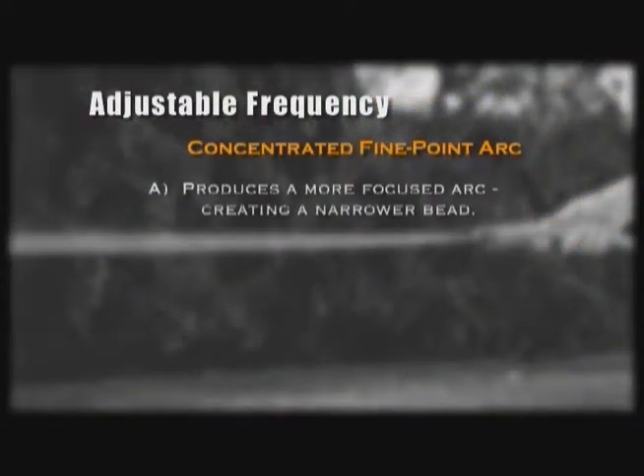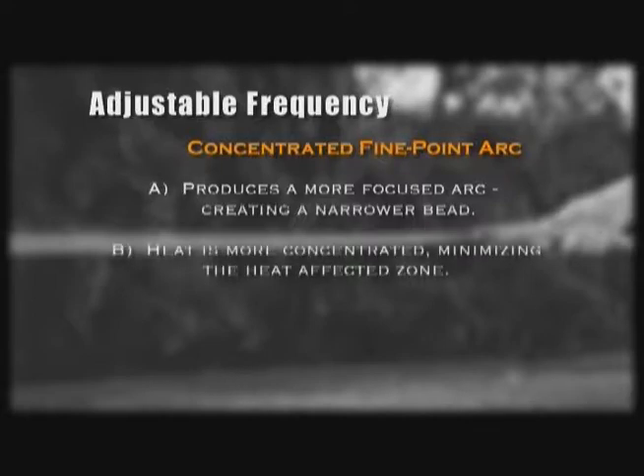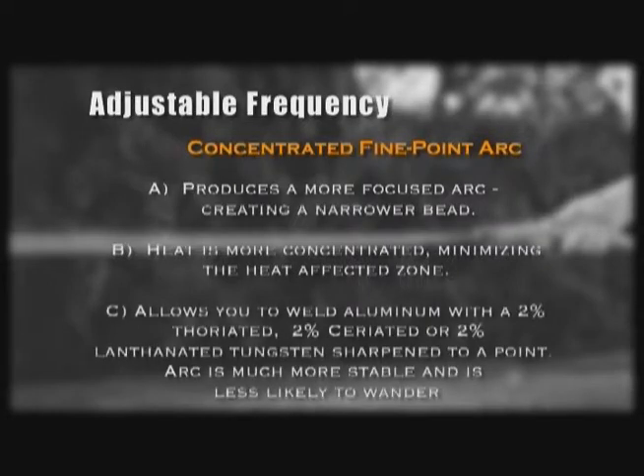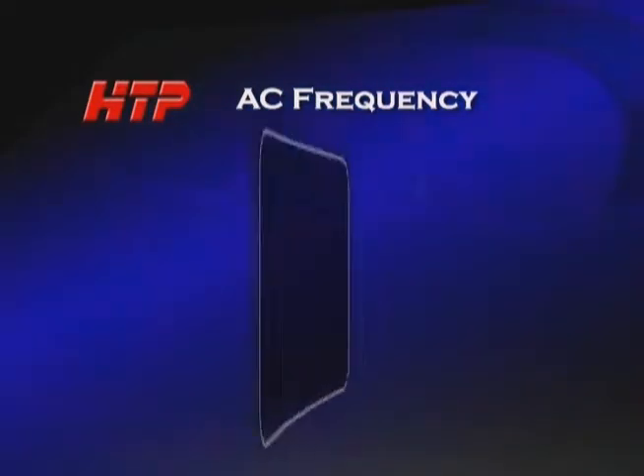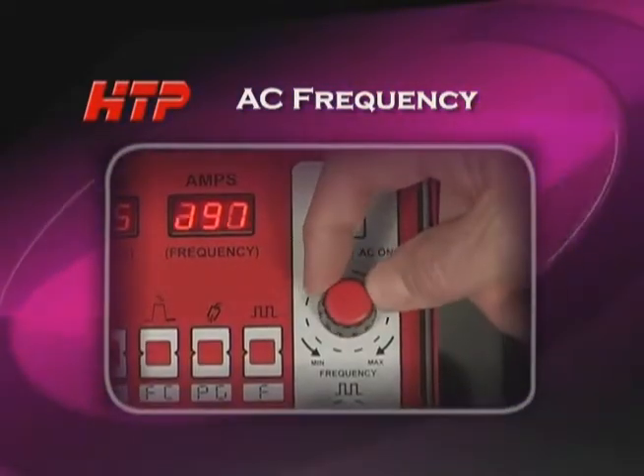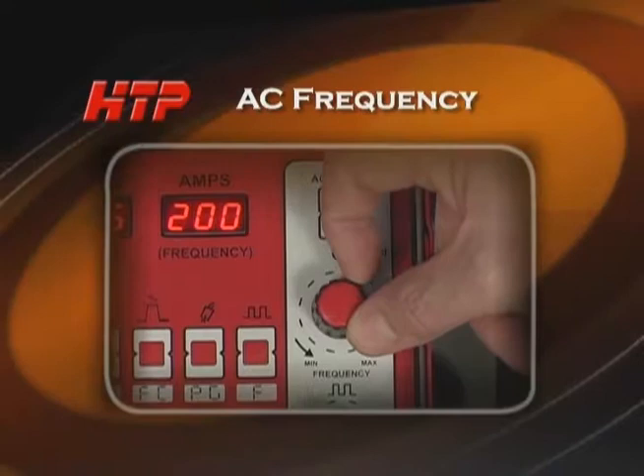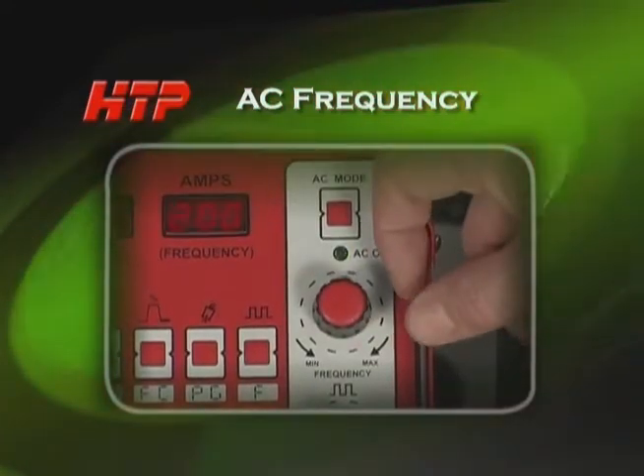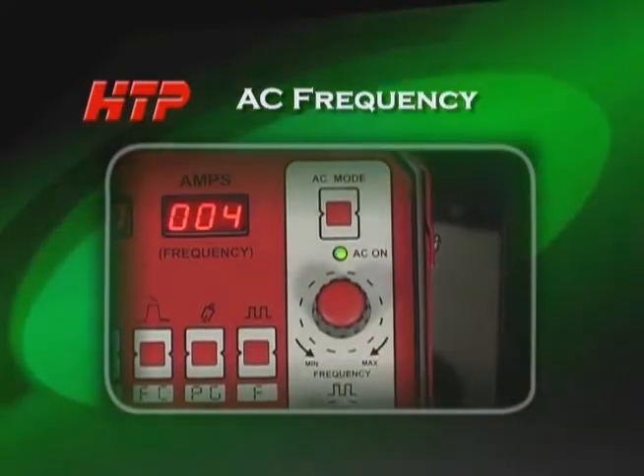Produces a more focused arc that results in a narrower bead. The heat is more concentrated, minimizing the heat affected zone, and it allows you to weld aluminum with a 2% thoriated, 2% ceriated, or 2% lanthanated tungsten sharpened to a point. The arc is much more stable and less likely to wander. To adjust the AC frequency, simply turn the frequency knob when the machine is in the AC mode. The amps display will flash and display the AC frequency.